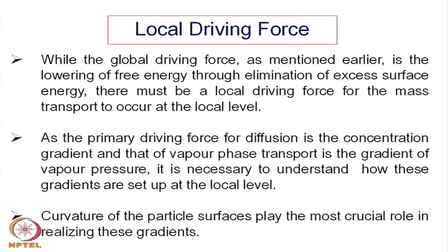We have earlier discussed that sintering takes place because there is a global driving force, that is the change of surface energy due to the change in surface area, and therefore the surface energy decreases, and therefore there is a driving force. The change of surface energy is the major driving force at the overall or global level.